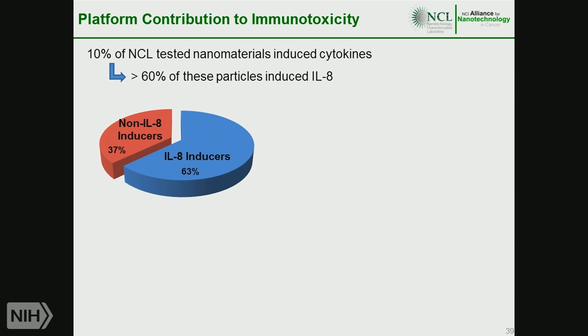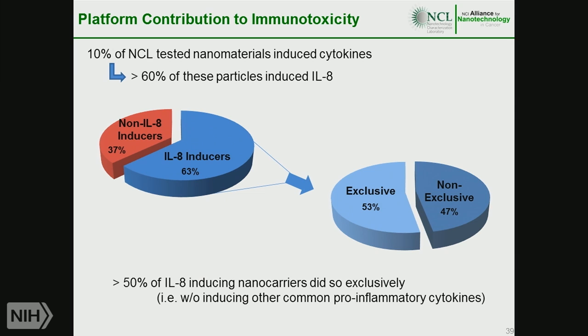So then I'll ask you, normally when you speak, for example, about bacterial contamination or bacterial ligands, like lipopolysaccharide, then you add it to your cells in vitro culture, or in animals, you see multiple cytokines, right? You see interleukin-1, you see TNF, you see interleukin-6, interleukin-10. In response to a traditional inflammatory stimulus, you don't see induction of interleukin-8 without induction of TNF and IL-1. With nanoparticles, what was striking for me is that we came across nanomaterials that induce interleukin-8 without inducing TNF and IL-1. So roughly 53% of these materials were exclusive inducers of IL-8. Exclusivity means they induced interleukin-8 without induction of TNF, without induction of IL-1.